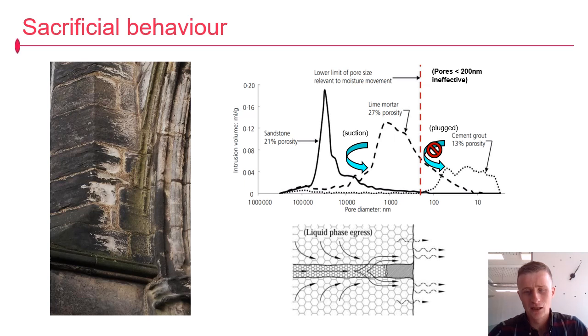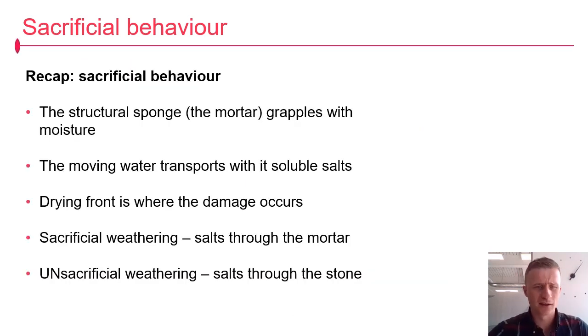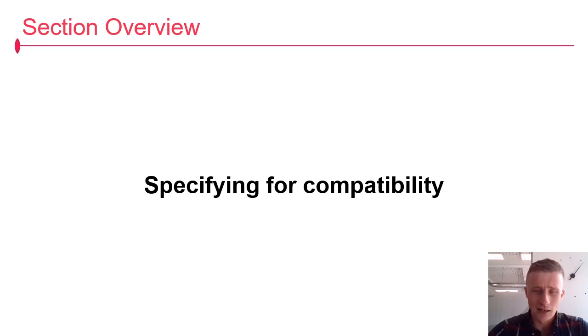So what you can see is the mechanics of the drying behaviour around the joint, shown at the bottom. The fine pored bedding mortar soaks the water out of the stone, but it's got to evaporate through the stone arrises to get around that plug, and that's why your arrises are weathering preferentially relative to your bedding, relative to the surface of the stone. Okay. So, quick recap on sacrificiality. The sacrificial behaviour of the lime mortar is just a direct outworking of its weatherproofing behaviour. The water management of the mortar is an outworking of its microstructure, and with that moving water come the soluble salts. Okay. Now, how can we replicate this process?